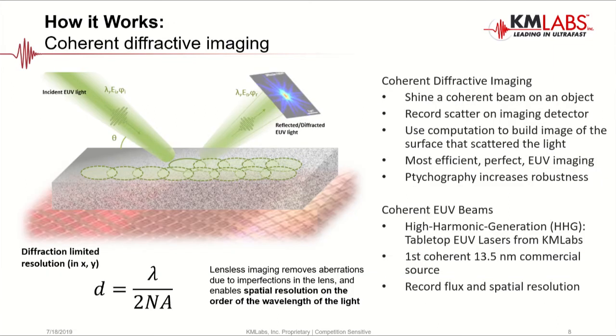And how do we actually do this? Well, we're going to use a technique called coherent diffraction imaging, where we shine a laser beam onto a sample. A diffraction pattern is reflected off of that surface, and we can image that diffraction pattern. And then we raster the beam across the sample with slightly overlapping spots, and we collect many of these diffraction patterns, tens of them, up to maybe hundreds of them. And then we can use a computer algorithm that will reconstruct these diffraction patterns back into real space, right? The diffraction basically represents a Fourier transform of the frequencies on the surface of the sample.